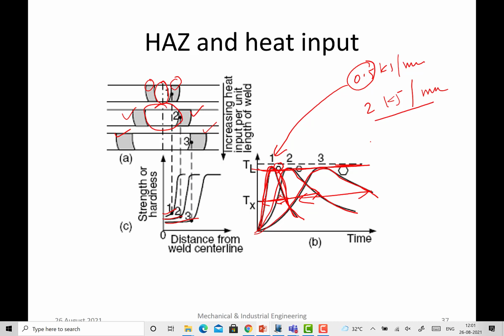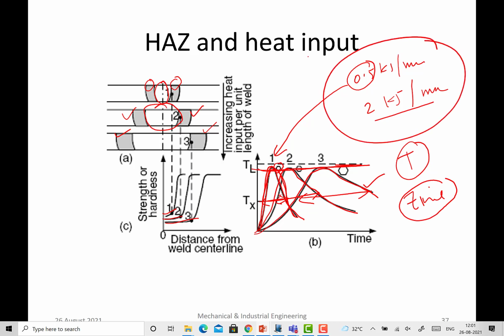Okay, so higher heat input means lower cooling rates and longer high temperature retention period. So these are the two factors which will be working against you, temperature and time. Both will be compromised with the increase of heat input, and that is why, it is very easy. When you have coarse grains, the properties will be further lower. That is what you can see here. The minimum hardness is also decreasing.